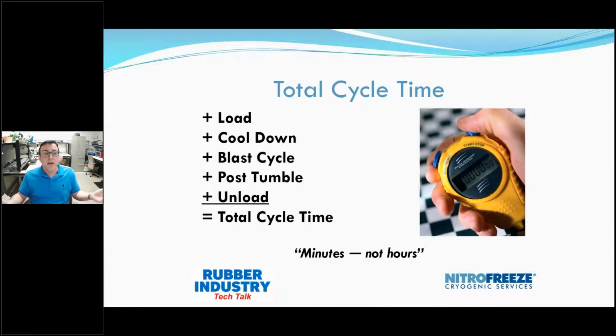So let's say we start at around freezing, say 32 degrees Fahrenheit. We go down to negative 180 to run a silicone part. Well, that can be seconds, it can be minutes. Every piece of equipment is different. For us, a cool down cycle to negative 180 degrees Fahrenheit could be a minute.